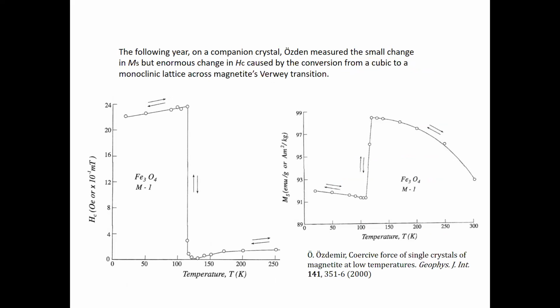Here, I guess this was in a following year. I don't know, it was year 2000, I guess it was published. You get a rather small change in the saturation magnetization when you go across the Verwey transition. It's less than a 10% change, in spite of this enormous change from the cubic to the monoclinic structure. But the change in coercive force is enormous, because of the enormous anisotropy of the monoclinic phase.